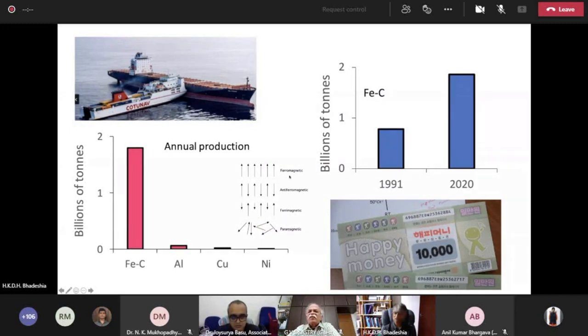For example, the magnetic transitions, which have a dramatic influence on the allotropic transitions in iron. So for example, pure iron starts off as body-centered cubic, then changes into face-centered cubic, and then goes back to body-centered cubic. And the reason for that is the magnetic transitions, which you don't see, influencing the free energies of the parent and product phases in a very large way. So there's no other system where you get this kind of a reversal from BCC to FCC to BCC. What that means is that you can engineer, control the microstructures on a large scale to get the properties that you want.